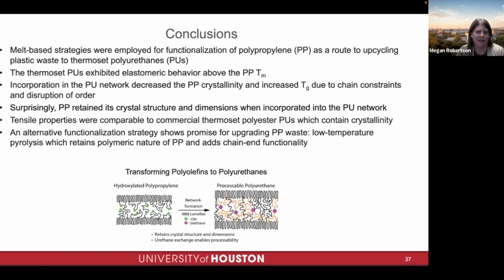Okay, I think I've come to the end of my talk. To conclude, we are trying to focus as much as possible on melt extrusion-based functionalization strategies for bringing new chemical features to polyolefins like polypropylene. Here we used maleic anhydride functionalized polypropylene as a starting point to form a polyurethane. These were thermoset polyurethanes, which is an important distinction because it opens up a lot of durable good applications. We confirmed that we had a cross-linked network because above the melting point, the storage modulus plateaued.